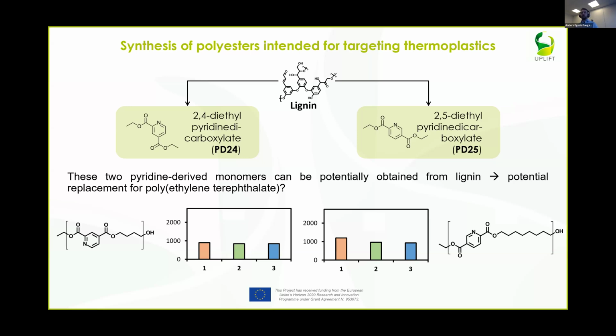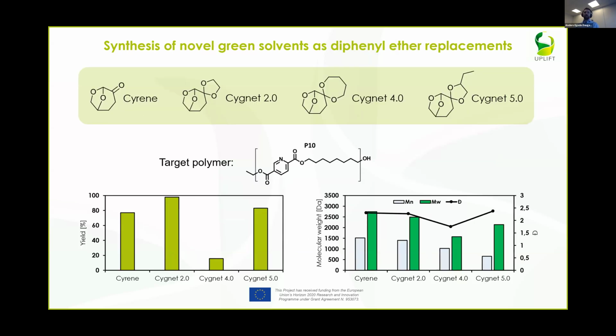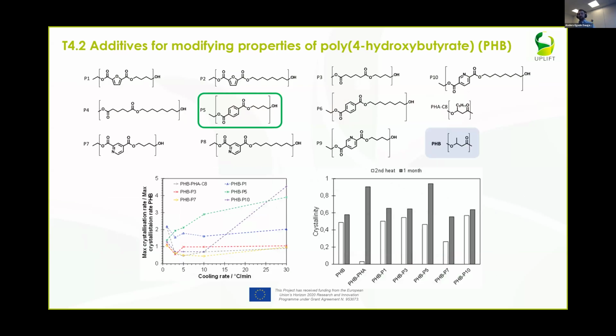One of the elements here is that enzymatic polymerization also often takes place in more harmful choices of solvents, and therefore an element here has also been the use of green solvents as replacements of diphenyl ether, which is a common solvent for these systems. And the work at ACID has looked into the development of the use of Cyrene and the development of Cygnet 2.0, 4.0, and 5.0, as you can see them here, and how that reflects their use in polymerizations for these low molar mass polyesters.